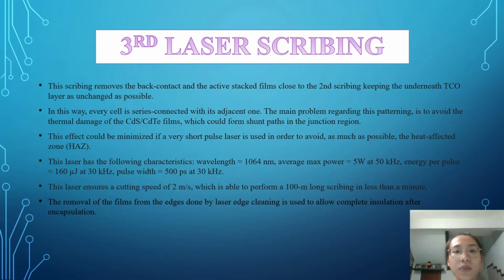So the next step will be the third laser scribing. This process is actually to remove the back contact and the active stack films close to the second scribing, keeping the underneath transparent conductive oxide layer unchanged. But there's a problem during this process, which is to avoid the thermal damage of the cadmium sulfide / cadmium telluride films, which could form a shunt path in the junction region.